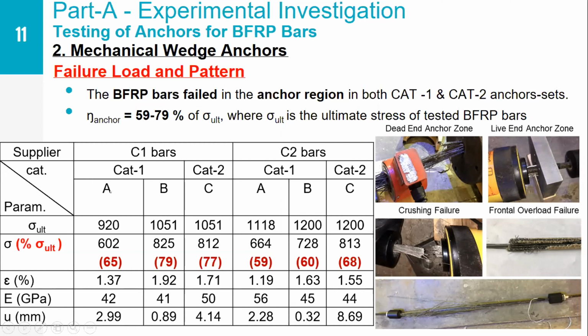A is for 12 millimeter diameter bar, and B and C are for 8 millimeter diameter bars. So the two different types of BFRP bars have been tested, and you can see that the rupture strength that has been obtained actually ranges between 59 to 79% of the ultimate strength of the bar, whereas the anchor efficiency that was obtained with the bonded anchor was much higher.